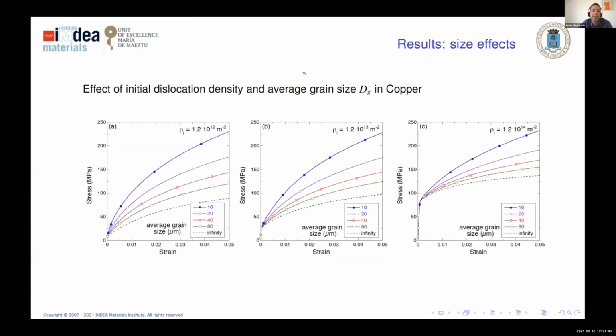And then we can see in this model the effect of initial dislocation density and average grain size. From left to right, we have different initial dislocation densities: 10 to the 12, 10 to the 13, 10 to the 14. These are stress-strain curves, only for copper. In the curves, we have the stress-strain behavior for a very large grain size, infinity, when size effects are not present, and different grain sizes from 80 microns to 10 microns.